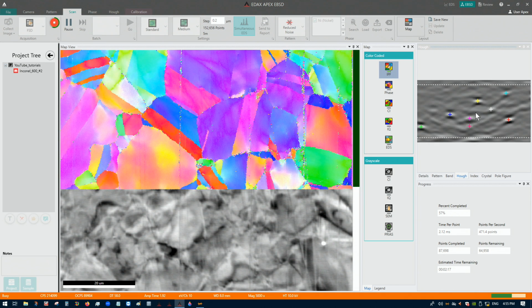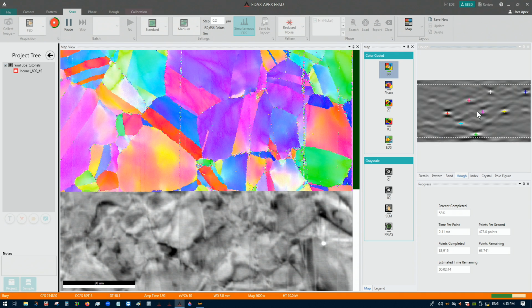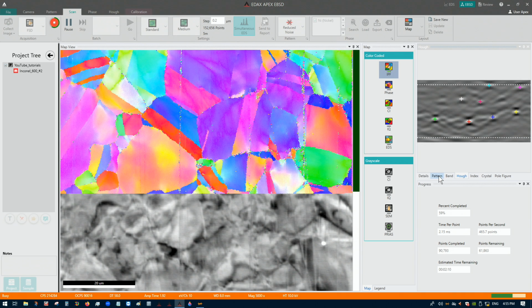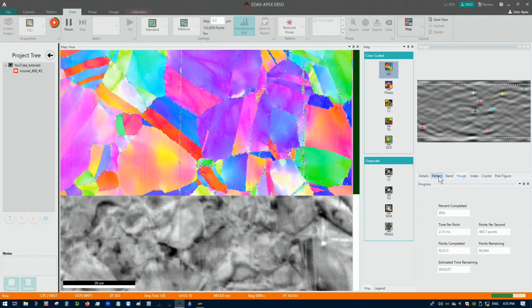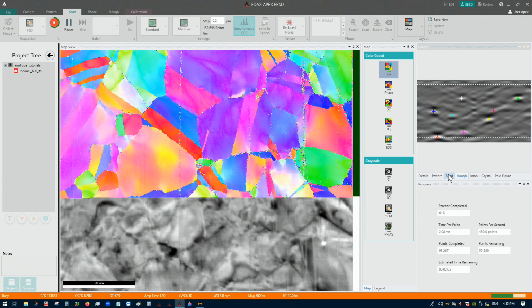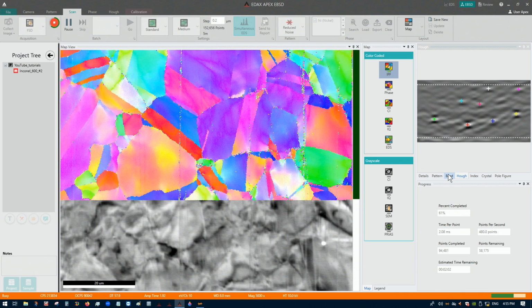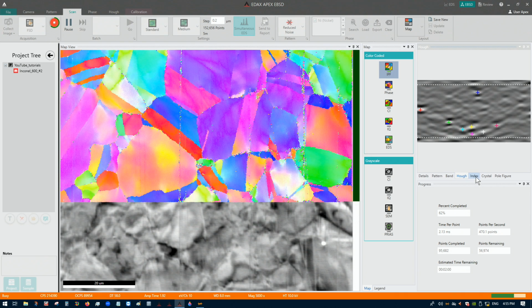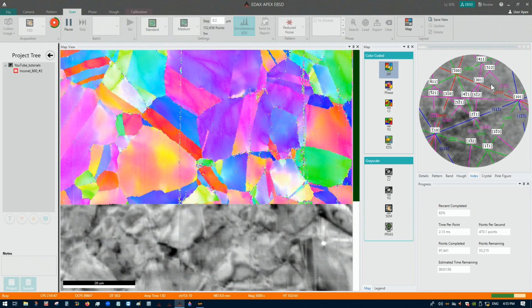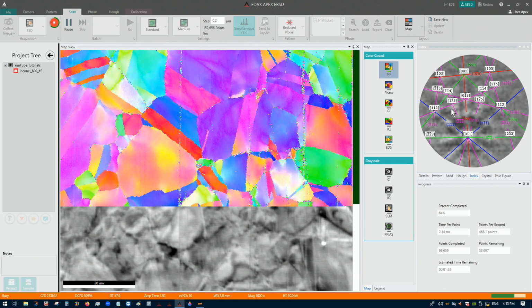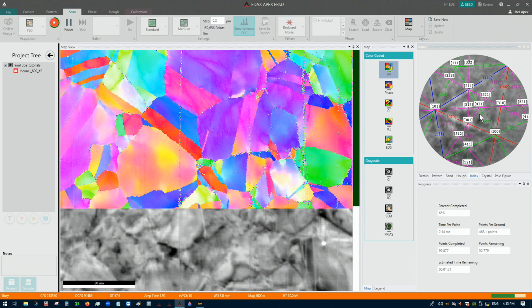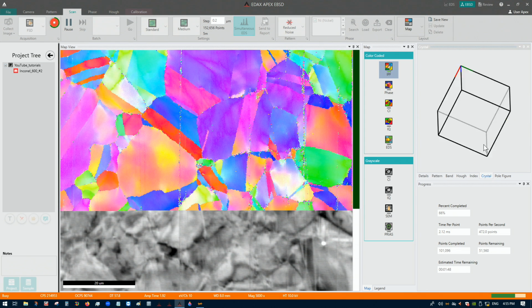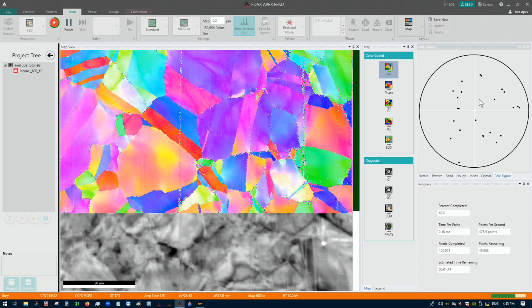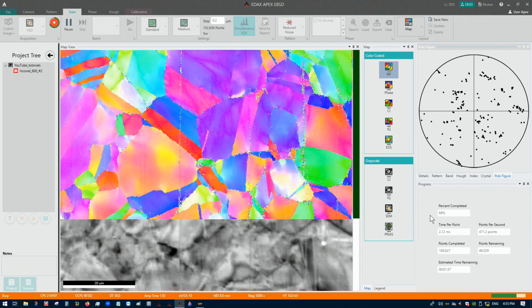Okay, and based on where these maxima are in the transform, that's telling us the orientation of the band as well as the width of the band, I believe. Okay, so this is how it's figuring out what orientation I have as well as what the crystal structure is. This is the solution, so it's telling us what the bands are, what the zone axes are, and this is the live crystal orientation as it's mapping. This pole figure, unfortunately, doesn't tell us which pole it's mapping here. I would think this might be 001, but I don't know. It doesn't say that, so it's kind of hard to make heads or tails of that.